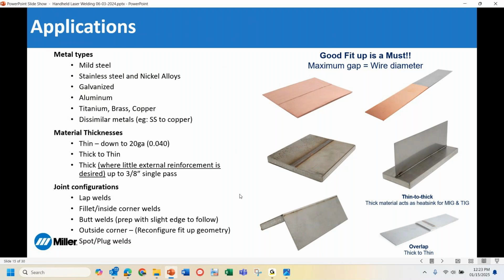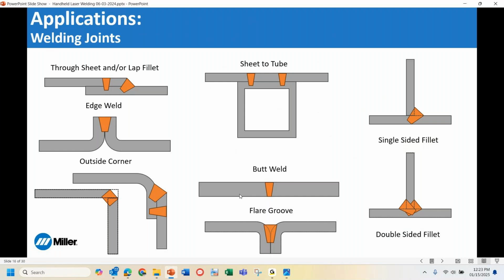I would say the sweet spot is really going to be in that 1/16 to 1/8 inch thick material range. And then when we look at the joint configurations, that's where it starts getting really fun. There's a lot of different configurations that we have, and it's important to be mindful of how we design parts to be conducive for handheld laser welding.